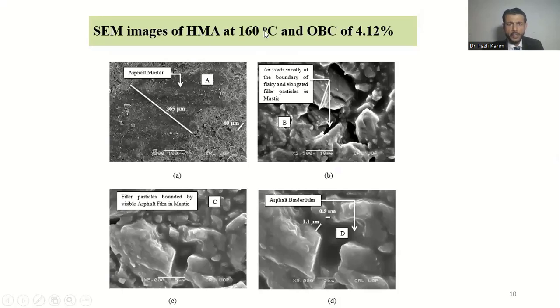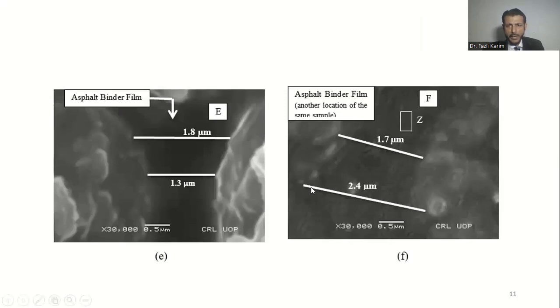Again, SEM images of the mix design at 160 degrees and optimum binder content 4.12%. Optimum binder content also varies with temperature. Asphalt mortar, and these are filler particles in the asphalt mastic. And one of the interesting findings of the study was the existence of emptiness or air voids even among the filler particles in asphalt mastic. This is filler particles of the mastic at another location of the sample. And this is clearly visible asphalt binder film.